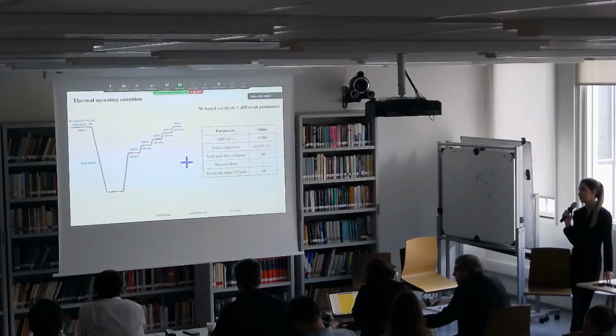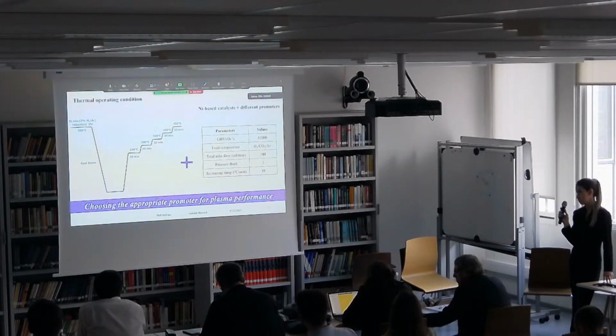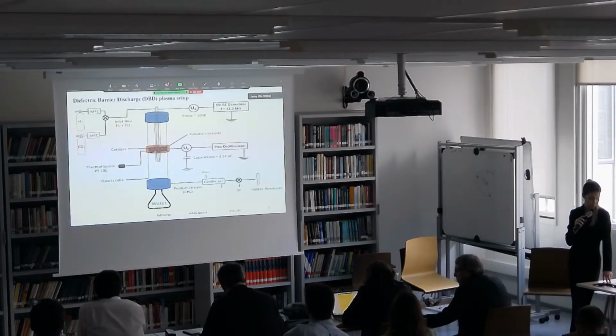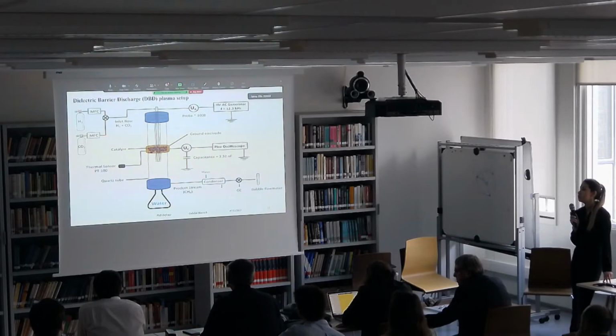At each step, the catalyst was kept for half an hour, and then the temperature increased with a ramp of 10 degrees per minute. The idea was to see the effect of promoters in this condition, to choose the best promoter for plasma application. Here is the scheme of the DBD plasma setup.